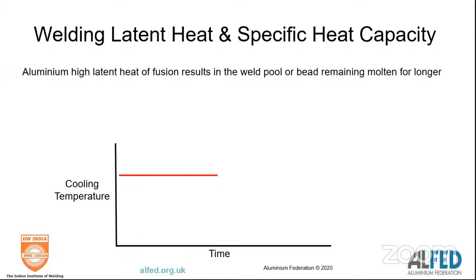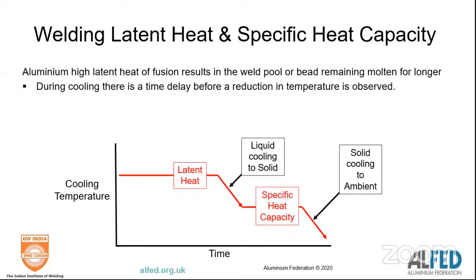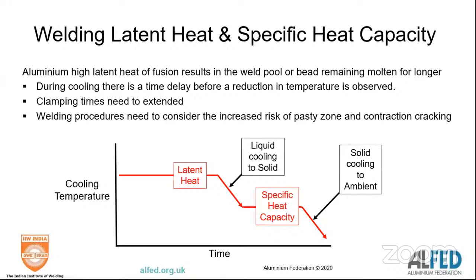High heat of fusion means that when we're solidifying from welding temperatures, it takes a lot longer to cool. So again, you now need to allow time for aluminium to cool. That means that your clamping times are extended, and you need to worry about contraction cracking in the heat affected zone.